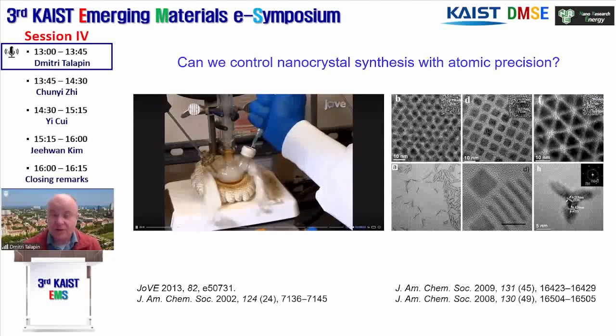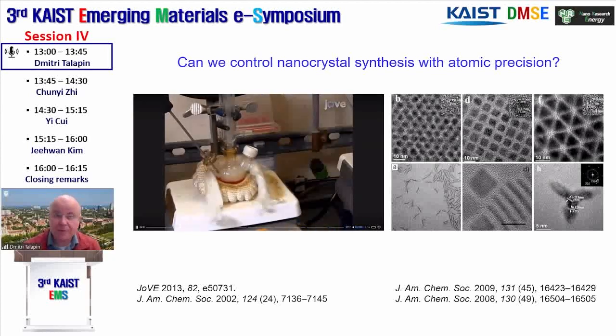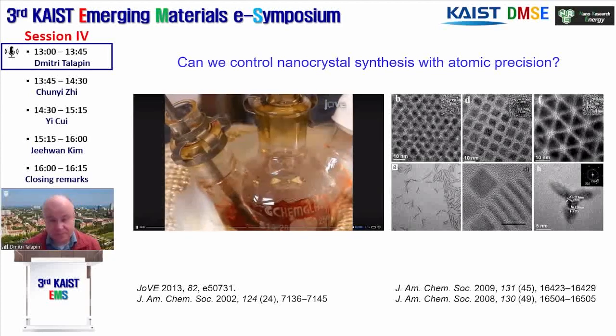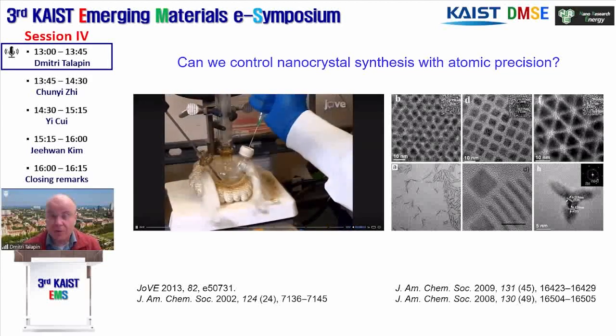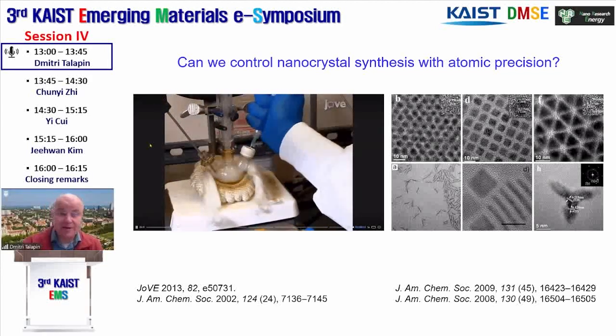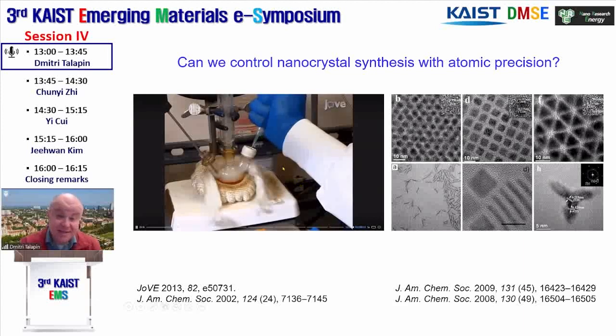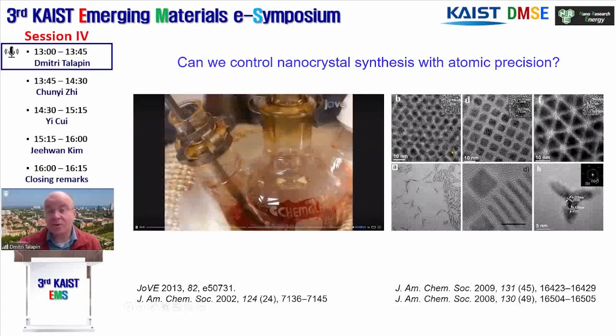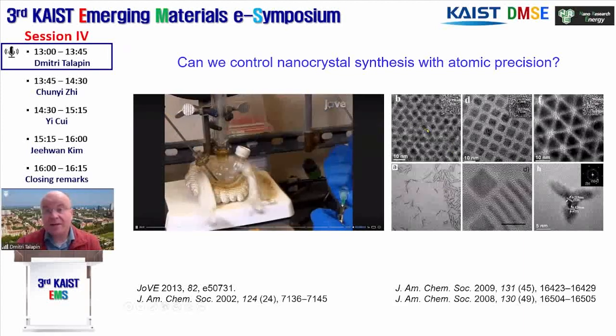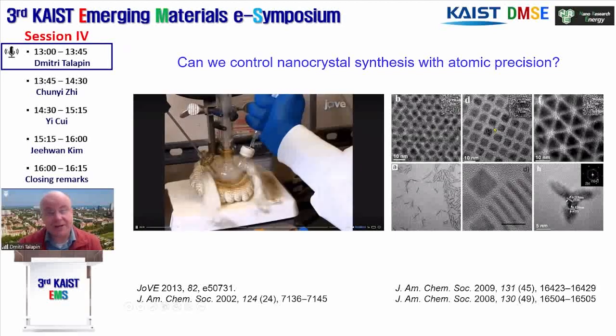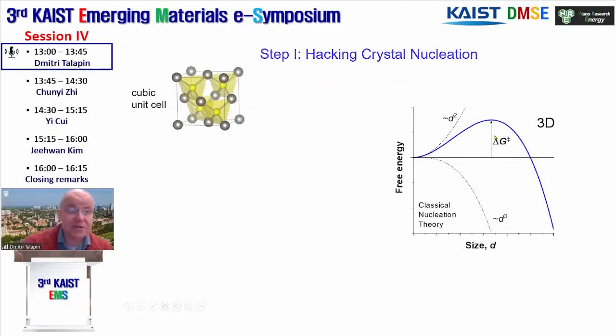The first is the nucleation. So the molecules nucleate and form crystals, and then these crystals grow. And depending on what type of chemicals we use in these flasks, we can control the growth to make spherical particles or shape-controlled particles and so on.